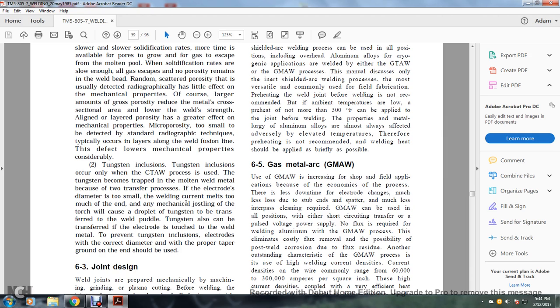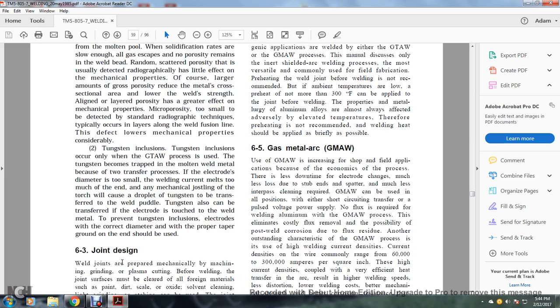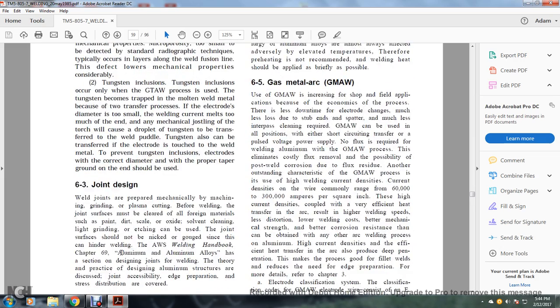Tungsten inclusion. Tungsten inclusion occurs only when the gas tungsten arc welding process is used. The tungsten becomes trapped in the molten weld metal. It can happen when the welding current is too high for the electrode diameter, or when the electrode is touched to the weld puddle and tungsten is transferred. To avoid tungsten inclusions, an electrode of the correct diameter with a proper taper ground on the end should be used.